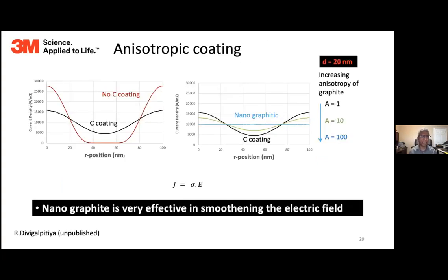On the right hand side, I show in red, without a carbon coating, the current density behavior at that nanometer size particle when we use this technique. Obviously we see large variation in the current density. If you put a thick carbon black coating, say 20 nanometers, we still see that change. Now, if you put a nanographitic coating, in the modeling you can just vary the anisotropy really easily. When you even hit 100, it becomes very apparent that the current density evens out quite nicely.